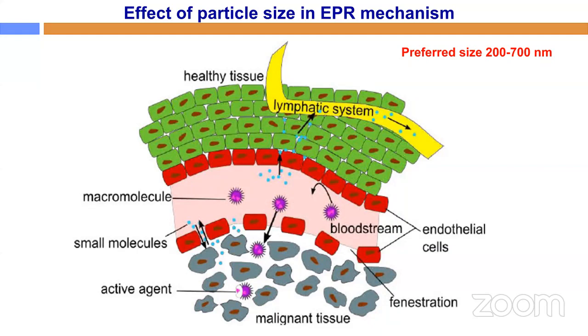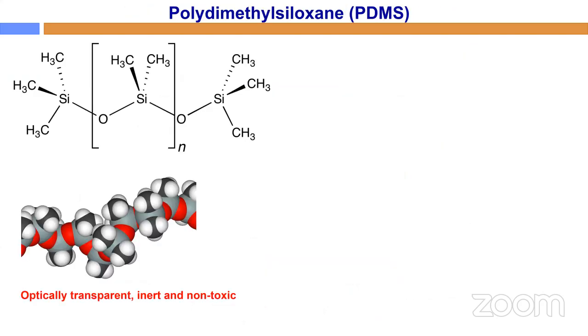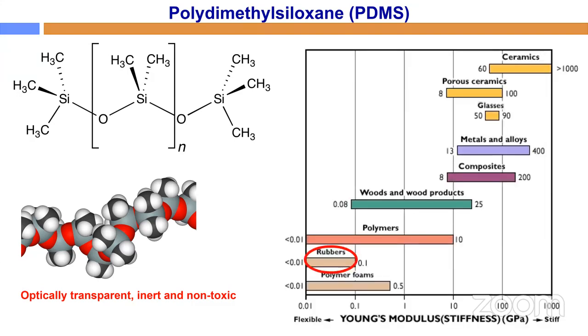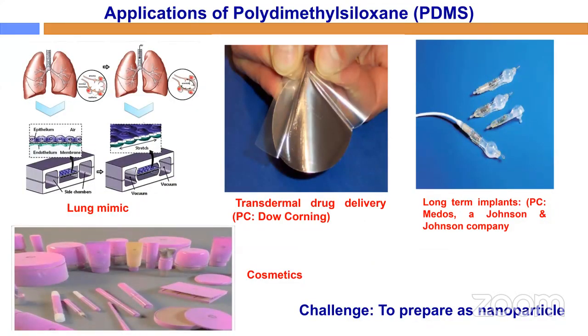So what we thought is, what if we can make a very soft, bigger nanoparticle? If it is soft, it can easily go into the tumor part because of the EPR mechanism, and it can go to the nucleus because, with its soft nature, it can squeeze through the nuclear pores. For that, we have chosen the polymer PDMS. PDMS is polydimethylsiloxane, a very well known, very soft polymer, optically transparent, inert and non-toxic, which has been used in many applications. Its Young's modulus is 0.1 GPa, so it is a very soft polymer. It has been used especially in lung mimics and implants.